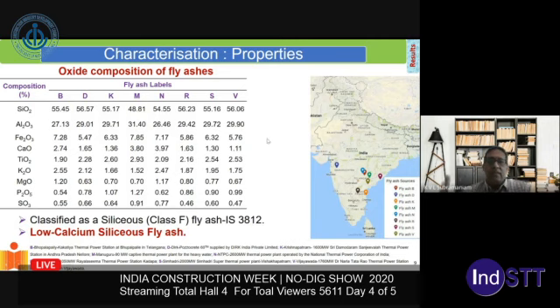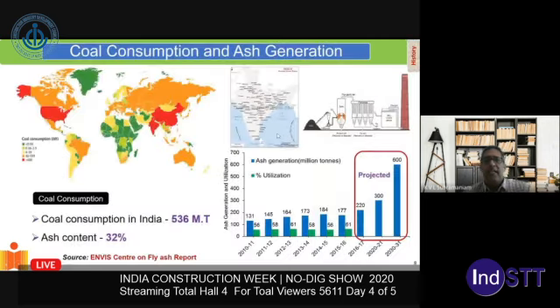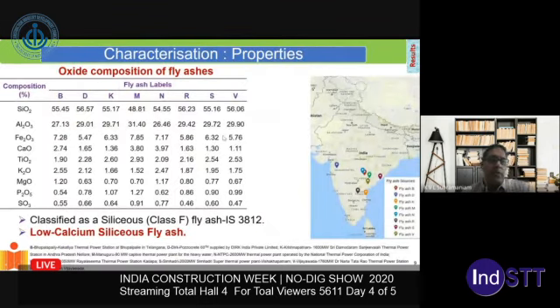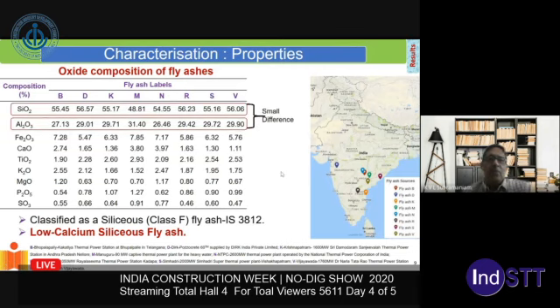So if you now look at the fly ash in India, if I just go to the previous slide, this map of India here shows the different thermal power plants in India, and there is an almost equal geographic spread of these coal burning power plants across India. But what we did, initially, to come up with solutions, is that we first wanted to understand this fly ash. So fly ash was collected from different power plants across the country, and it was analyzed. And what we found is that if you look at just the oxide compositions, there is a very small difference in the oxide compositions of this fly ash. But when we started using this fly ash in concrete, we found that the results were night and day. There was a big difference in the final strengths, the final properties that were achieved with these fly ashes. So to understand that, we had to do a higher level of characterization.